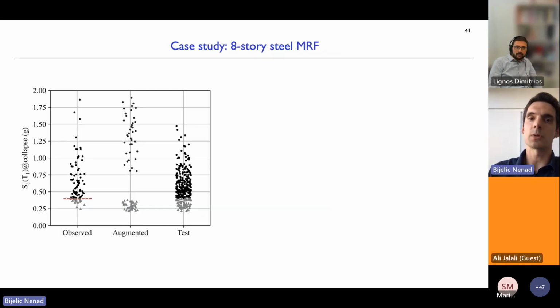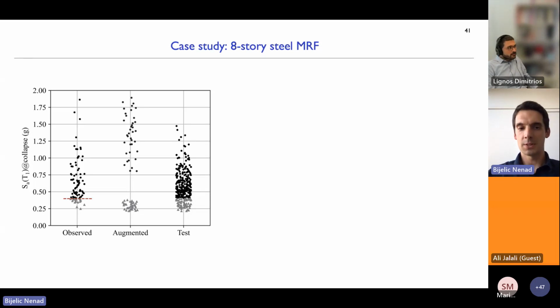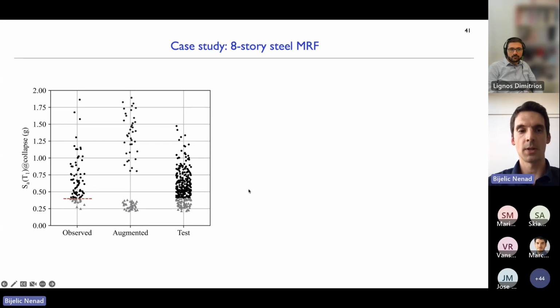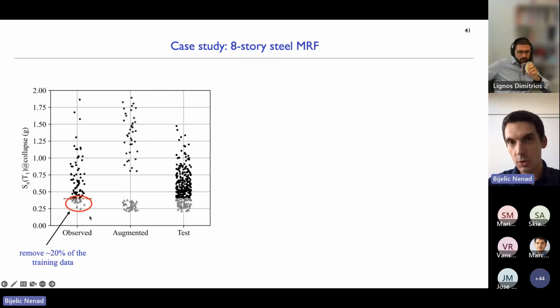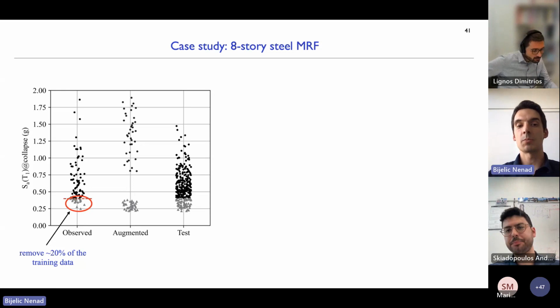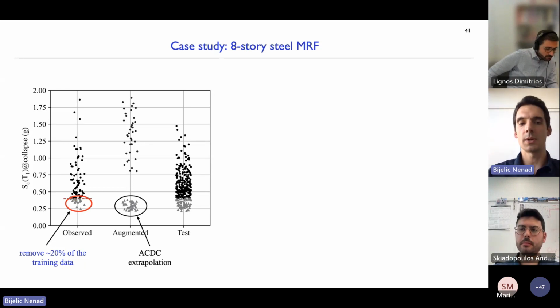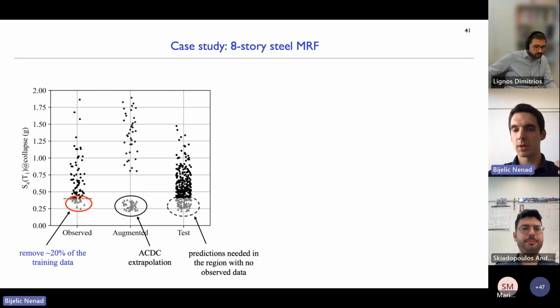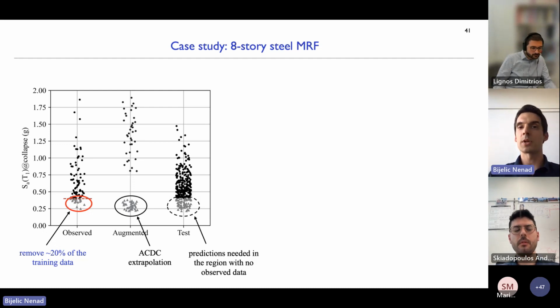Okay. So now, finally, for the results. Shown on the left are the strip plots like you've seen. We have the observed data we start with. In the middle is the augmentation I do using AC/DC, and then on the right is our test set. Now, to make this problem harder, we removed 20% of the training data from this bottom part, which shows the lowest part of the collapse fragility. This implies that the augmentation here will have to be done using extrapolation because we don't have any training data there, but also predictions will have to be done in a region where we don't have training data.